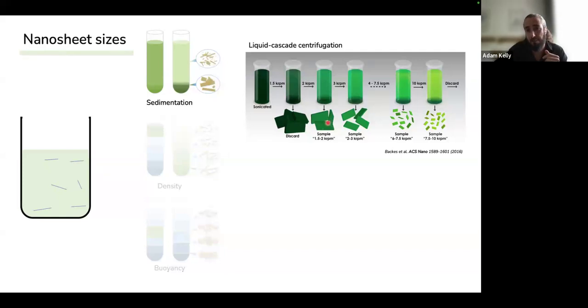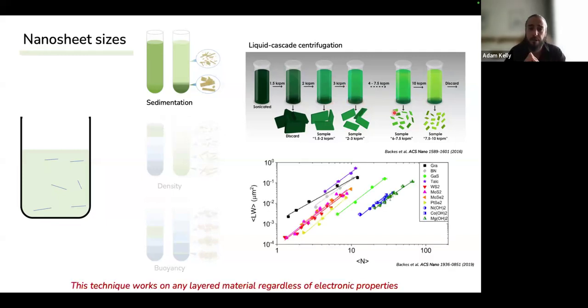We will take this and keep it for processing, and then we can continue this process, taking the supernatant, taking the sediment, and work our way up, getting a range of different lengths and thicknesses. So yeah, as I said, this technique works for any layered material. This is great. It doesn't matter what the electronic properties of the material are. We can do it with graphene, we can do it with talcum powder, we can do it with tungsten disulfide, platinum diselenide, all of them.